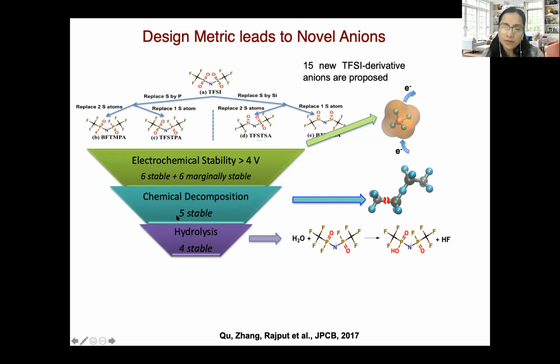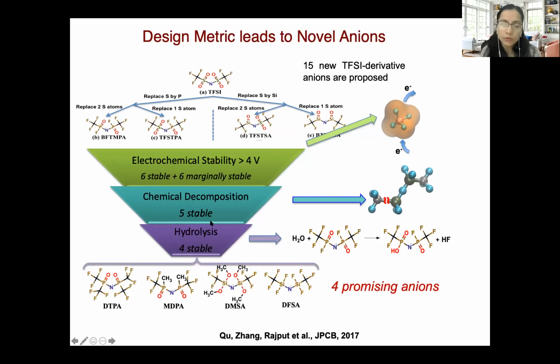And then finally, we tested them for hydrolysis, because water can be present as an impurity and can lead to decomposition of the anions. And finally, we were able to screen 4 promising anions with much better electrochemical and chemical stability and a lesser degree of forming ion pairs with magnesium ions. Okay.